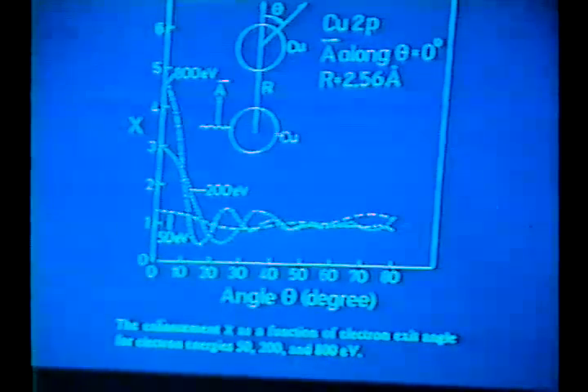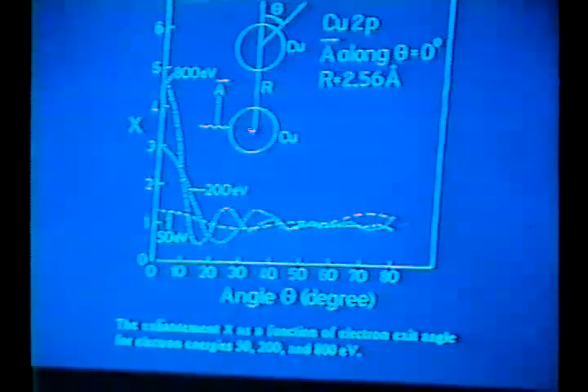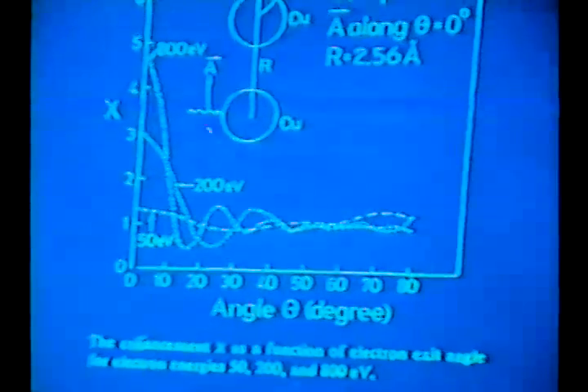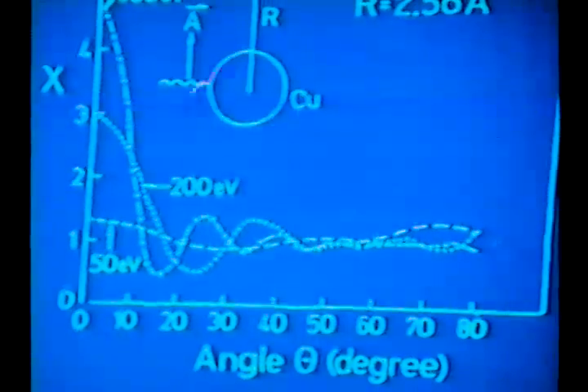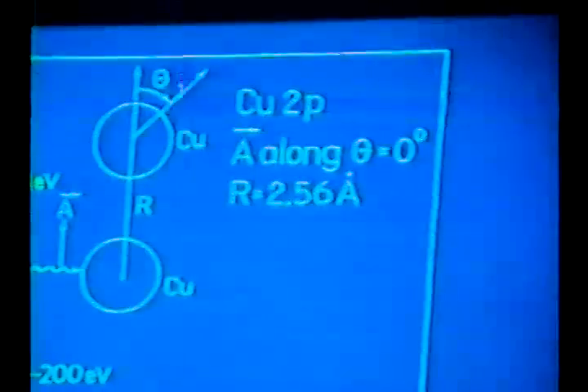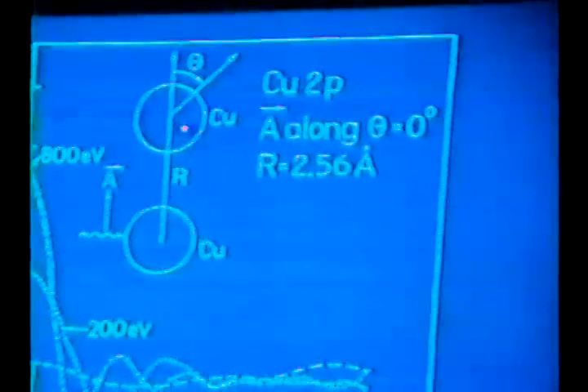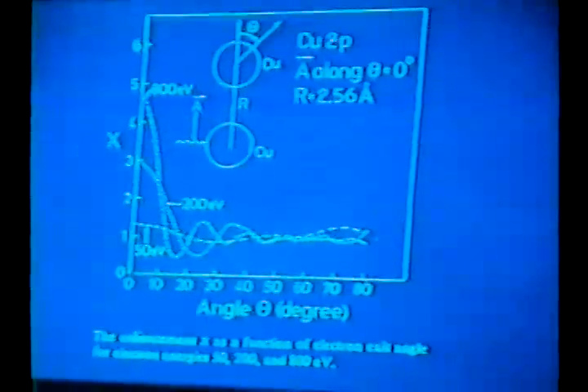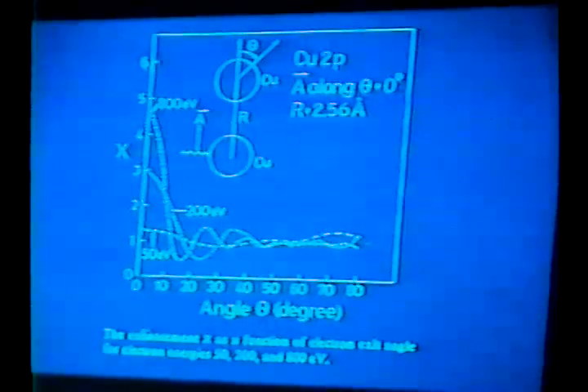There is an emerging way of doing structures by XPS, and there is a hope that surface structures can be determined to within 0.01 angstroms. The structural work is based on forward focus diffraction, here exemplified in a scatterer and an emitter atom. The copper is irrelevant because it can be done with any element. This is the atom that emits a photoelectron. This is one that scatters it.